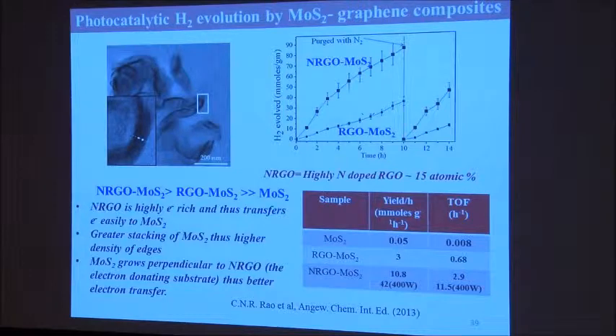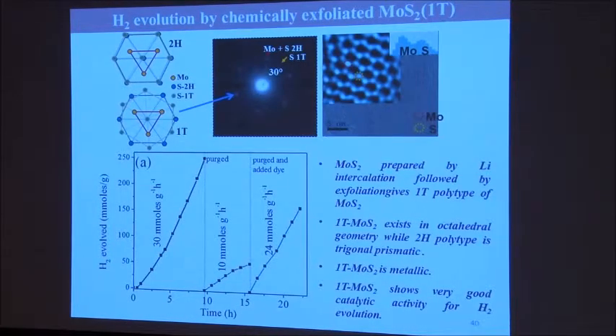Well, if this is the case, why not do something with molybdenum sulfide itself? Forget about graphene—why do I need graphene? So in this process, what we did was make a new kind of molybdenum sulfide. This is where chemistry and material science come together—somewhere in the back of my head I knew if I did some alkali metal intercalation in molybdenum sulfide and exfoliated it in some way, you get a new form of molybdenum sulfide. Ordinary molybdenum sulfide is 2H polytype.